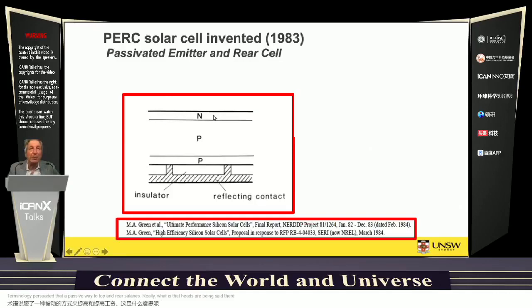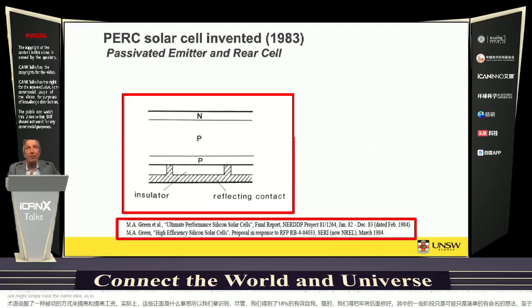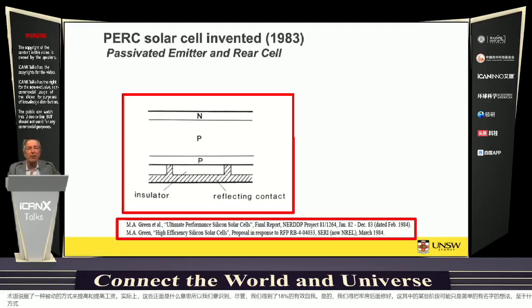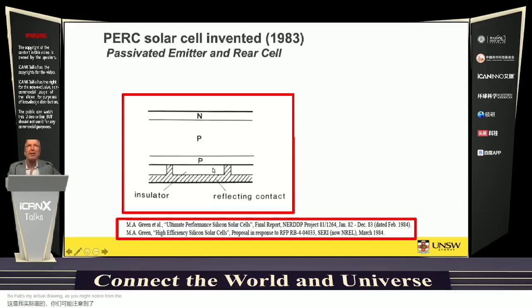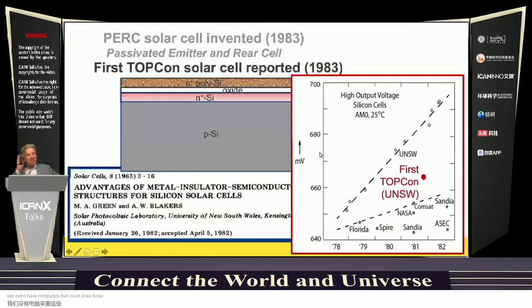So we realized that, though we'd fixed up the top to get our 18% efficient cell, we were going to have to fix up the rear of the cell at some stage, and this was just my idea as to what the best way of doing that would be. So using oxides again to passivate most of the rear and having small area contacts to the rear to reduce the detrimental activity of those rear contacts. So that's my actual drawing, as you might notice from the wobbly printing on it. We didn't have computers that could draw those for us back then.